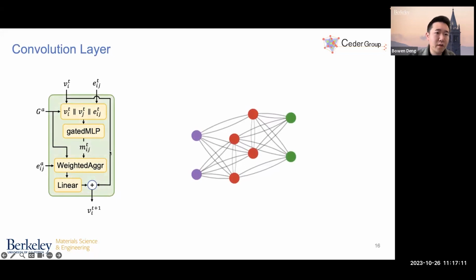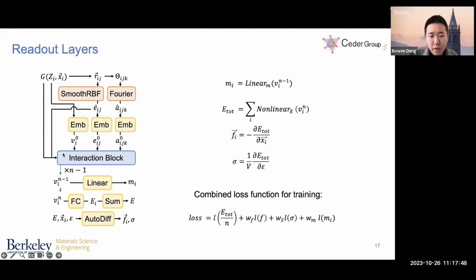If you look at what happens within each convolution layer, it's really a simple process. We search for all the neighboring atoms for each atom, and in this case, it's for the atom graph. We search for all the neighbors for each node, compute their pairwise messages, and then aggregate them to the receiver node. That's how an atom can receive the message and information from all of its neighboring atoms. After we perform n interaction blocks, which in our pretrained model is 4 interaction blocks, we reach effectively a 20 angstrom interaction radius, and also many-body interactions.